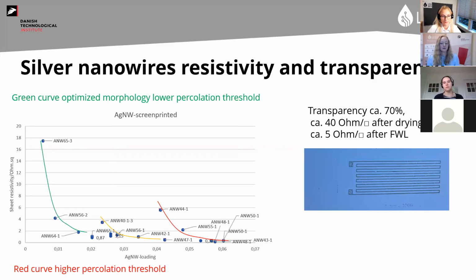So we want to work in a certain area, but that means also that if you want the smaller sizes or longer wires or something like that, you might need to use more of, for example, PVP in the production, and that could maybe have an influence on when you do ink and when you do printing. So we always need to be aware of where is the optimum between what we are putting in the synthesis and what is actually coming out.